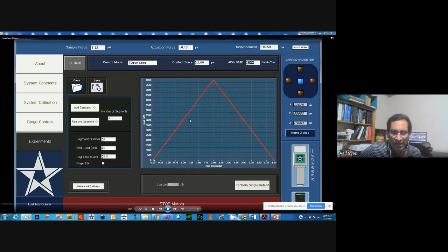For example, here I'm starting with 0 load, and then it goes up to 8000 micronewton load in the first segment, and then immediately unloads to 0 load in the second segment. That is what is being shown over here. Okay, and then you can add segments or delete segments from this interface, and you can also change the load or the displacement with that interface.